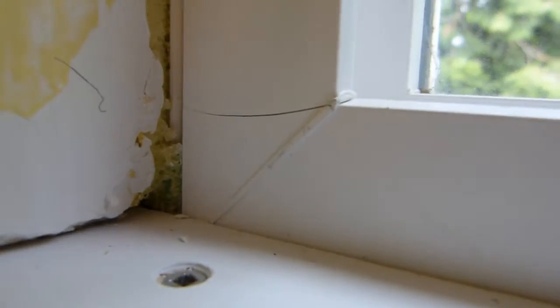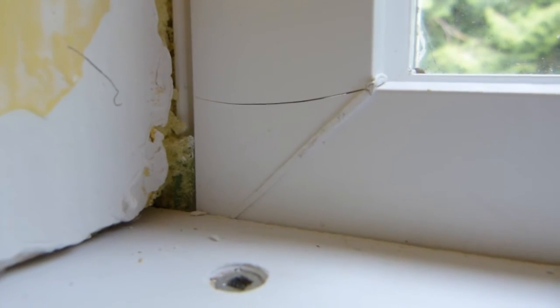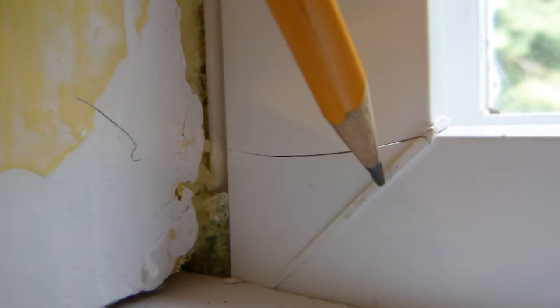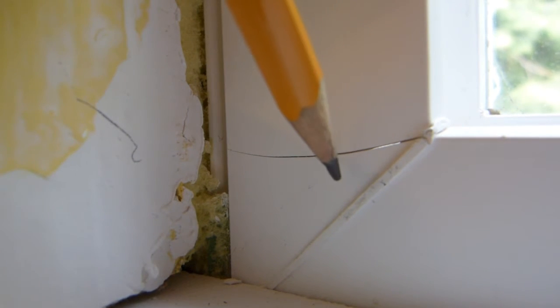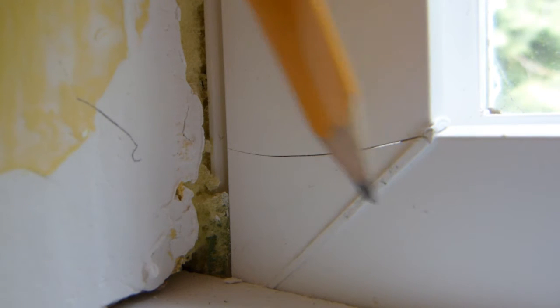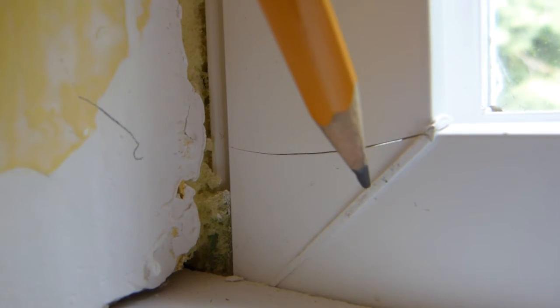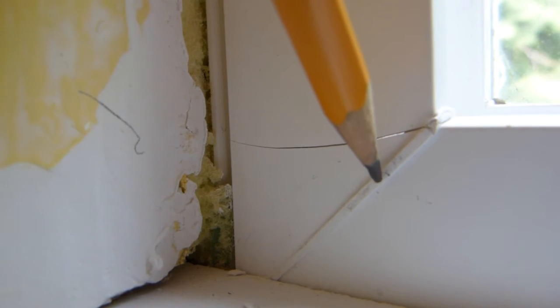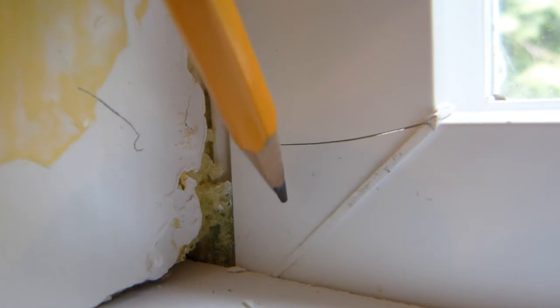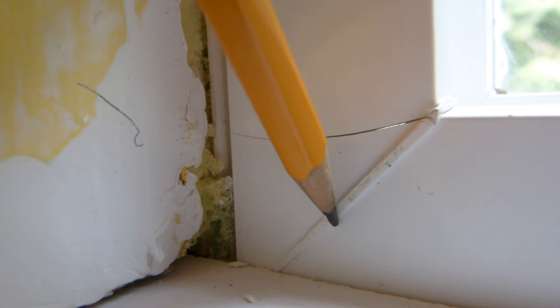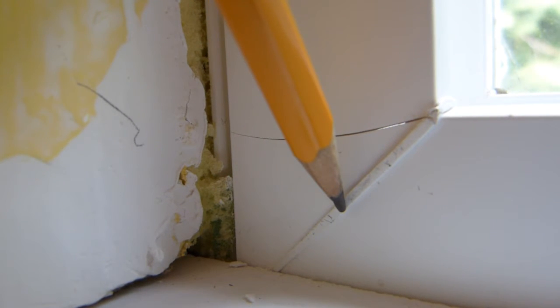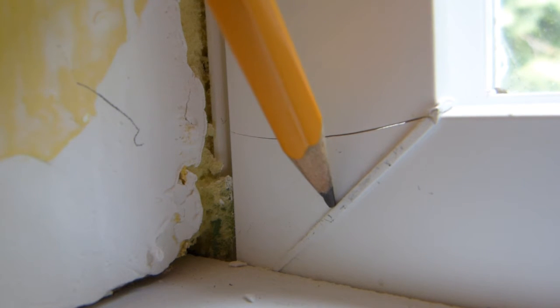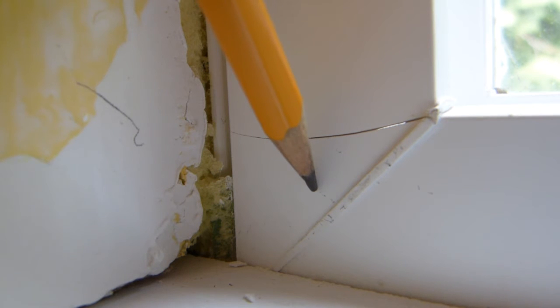So this is a manufacturing mistake which is caused by thermal shock. This thermal shock is due to this plastic weld here. To join this piece and this piece together, the ends that meet at this miter need to be heated up to a melting temperature to ensure proper fusion and proper joining between these two plastic pieces. Much like in welding and joining metal, there is a heat affected zone. So if the melting temperature here is, say, 150, then the temperature here is 130, 110, 80, 70, 60. You get the idea.